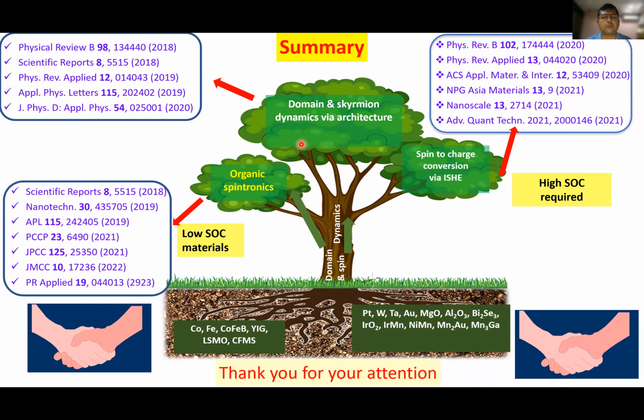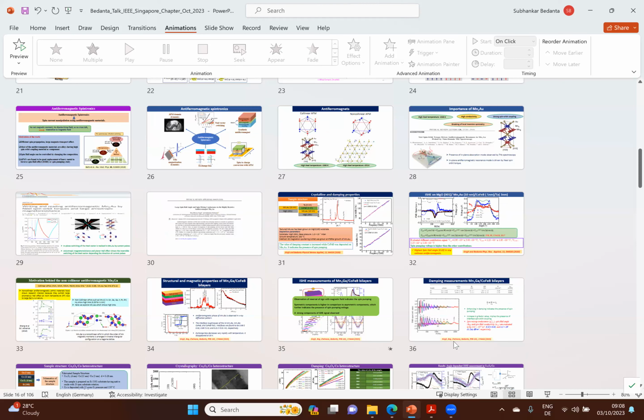You have the Mn2Au work, where you found the spin-Hall angle is 0.52. So if I compare with platinum, in terms of resistivity and spin-Hall angle, how comparable is the Mn2Au spin-Hall angle with respect to resistivity?